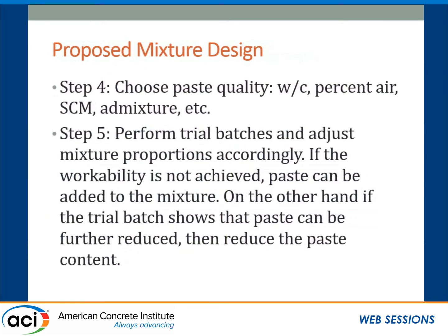Now we know the void content. This void content is equivalent to our paste volume content, because theoretically the paste volume should fill those voids. I will be calling this void content the theoretical paste volume requirement for the concrete, and this is our first initial paste volume for the concrete mixture design. We then choose the paste quality — meaning what kind of material to use, including supplementary cementitious material — and make sure that is accounted for in the concrete. Finally, we go through trial batching to reduce or increase the paste volume to get the physical properties we need.